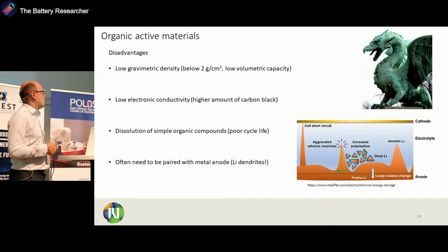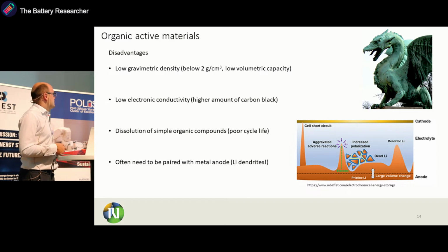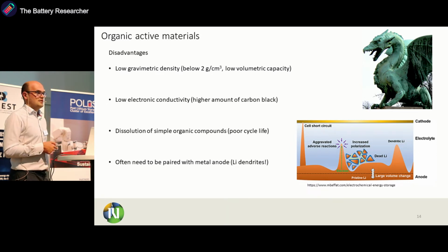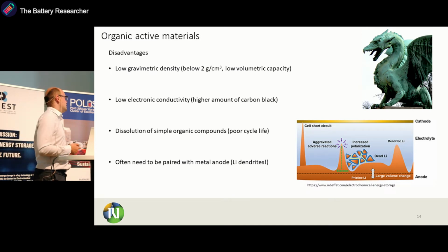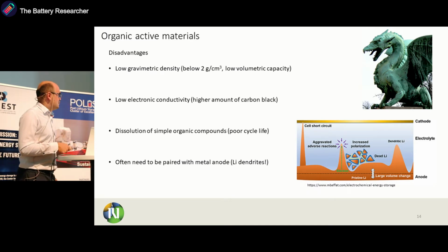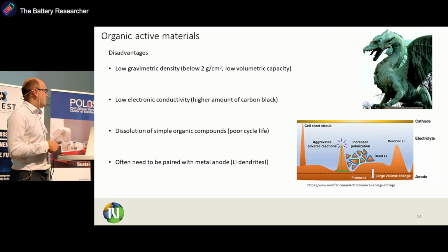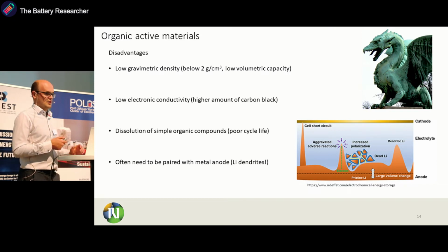Additionally, there is low electronic conductivity, which means that we need to add relatively higher amounts of carbon black. And simple organic compounds often suffer from dissolution, so it leads to poor cycle life. So we have to somehow mitigate this. And if we speak about lithium organic batteries, we often need to pair them with metal anode, which leads to lithium dendrites.